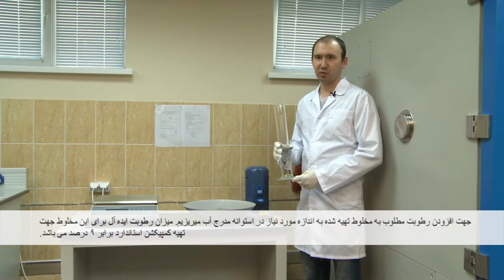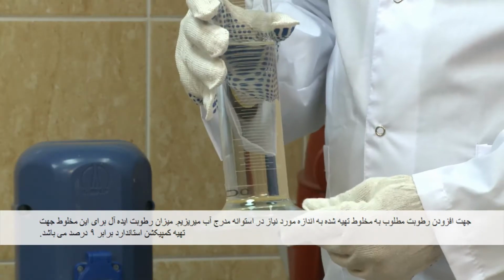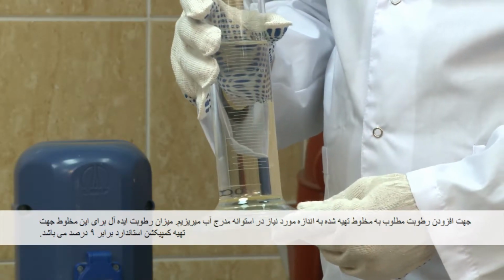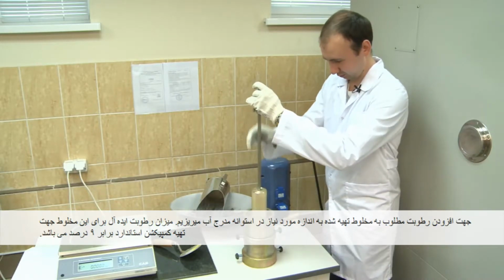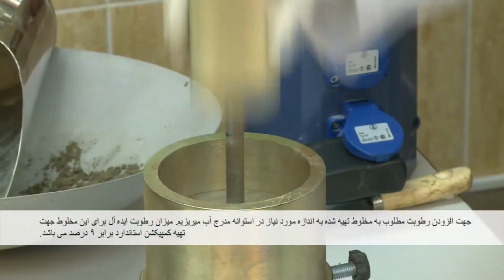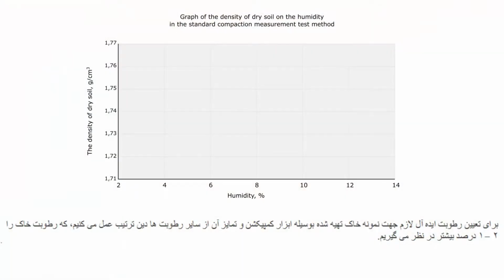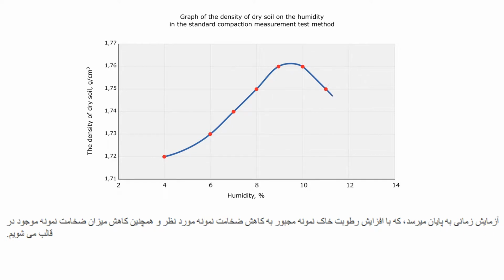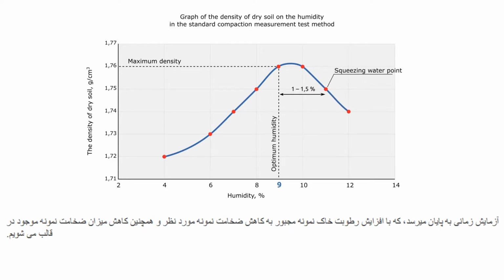Let us pour in the amount of water sufficient to obtain a mixture with optimum humidity. Optimum humidity of this mixture was discovered earlier when making samples with the use of the standard compaction measurement device. This value is 9%. To determine optimum humidity, soil samples were produced using the standard compaction measurement device with different humidity, and every humidity value of obtained soil was 1 to 2% higher than the previous one. Tests were considered complete when humidity increase of soil samples was accompanied with a decrease of density of the tested soil. Water was squeezed out from the standard compaction measurement device during production.